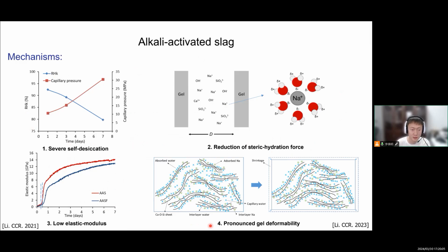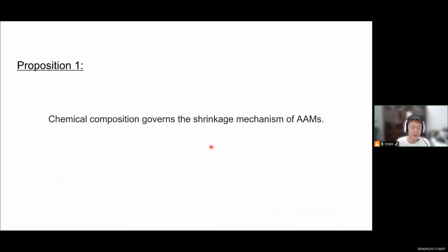So here I would like to propose something. When we look at the shrinkage mechanisms, we should not look at the terms or names of the materials. For example, fly ash and slag are both byproducts, but they have totally different shrinkage mechanisms because they have different chemical compositions. One is silica rich, one is not. One is calcium rich and one is not calcium rich. And we also call it geopolymers or alkali-activated materials. Actually, the names are not so important.